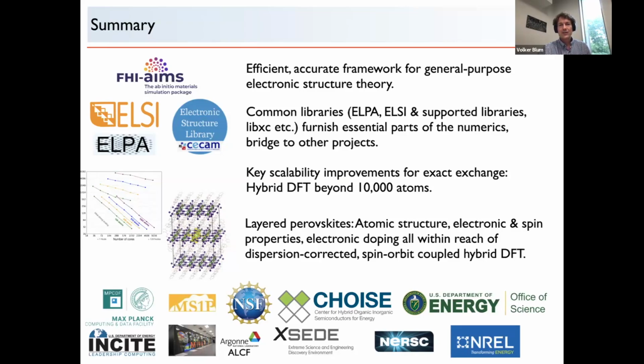And this is all a very detailed and careful benchmarking exercise for any single property. And with all electron codes, you simply don't have that problem, especially if you can do the same thing faster anyway, right? So for the systems that I showed here, I think we're actually pretty fast. So this is not our problem. So we don't have to worry about artifacts like the lithium bulk modulus, which at the time was very wrong in a production pseudopotential that I actually tested. And so I think this is the important part. So you have to do a lot more benchmarking. And in fact, I think FHI-aims in theory could be run with pseudopotentials, right? It's just that you have to do very, very detailed benchmarking. And so with the all electron approach, we do not have that problem. We can just run, and so we don't have to parameterize anything underneath. And this for me has been a big advantage over the years. We can test.